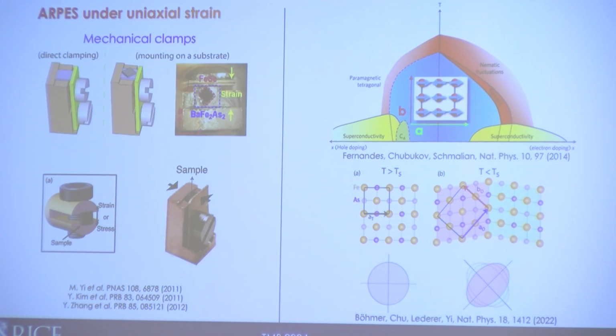What's interesting here is that you see this phase diagram. Here our horizontal axis is doping. These are the superconducting domes. And then the parent compound lives in this region where there are a couple of symmetry breaking phase transitions. So here in this white space, the normal state, this is a C4 rotationally symmetric phase. And then when you enter this blue region, this is a collinear spin density wave order.